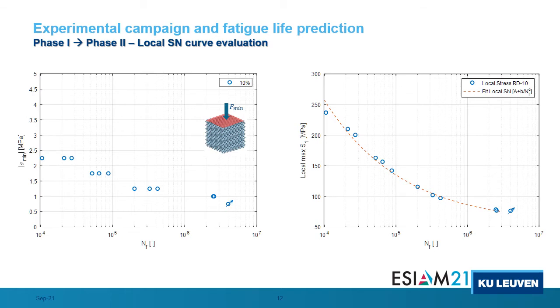Fatigue test results of phase 1 are presented in the graph on the left. 5 different stress levels were considered between 0.75 and 2.25 megapascal, with consequent fatigue lives varying from 10,000 to 4 million cycles. The graph on the right side shows local SN data that we extracted using the experimental results of phase 1.